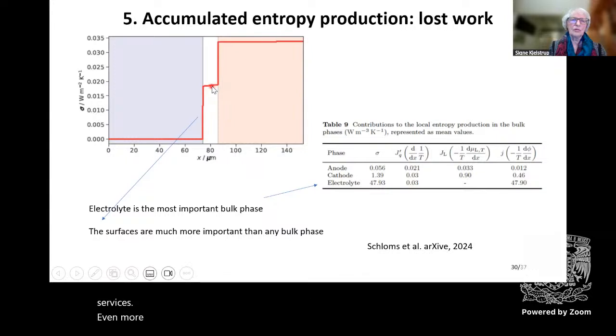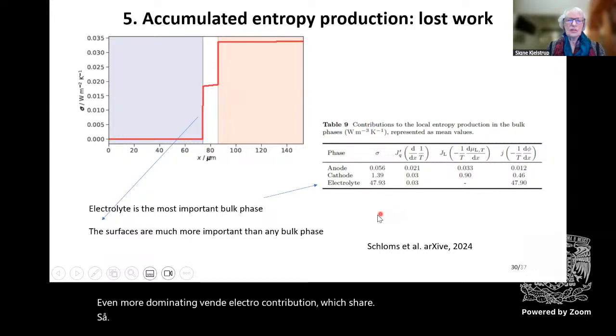The accumulated entropy production is a measure of how much we lose in work without gaining anything. And here you see a very clear message. The electrolyte is so much more important than the anode and cathode bulk phases, that is. But if we look at the figure, we see that still the surfaces are even more dominating than the electrolyte contribution, which is here. So this is, of course, important to know.